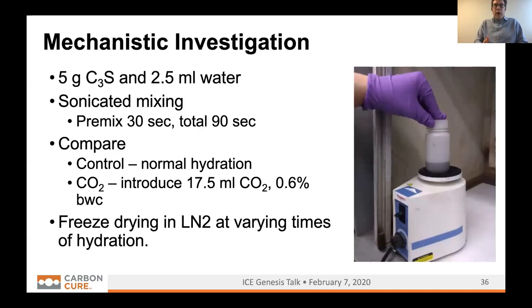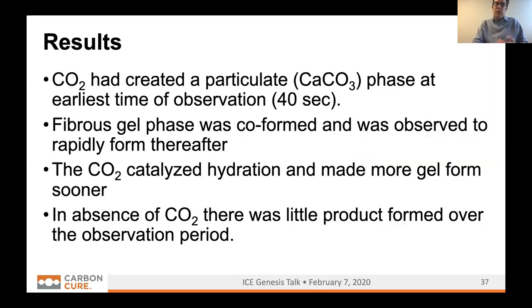Now, why would the addition of CO2 provide a compressive strength benefit? This is part of ongoing investigations for us. So we've looked at what happens if you take tricalcium silicate paste and then you mix it up and then you add some CO2. So we added a dose where we could observe products being formed, and then we freeze dry it to stop the hydration. And so what we're observing is that this CO2 creates this particulate calcium carbonate phase, even as early as you want to look at it. In our case, this was 40 seconds after the injection of CO2. So this is certainly, while the concrete is still being mixed at 40 seconds.